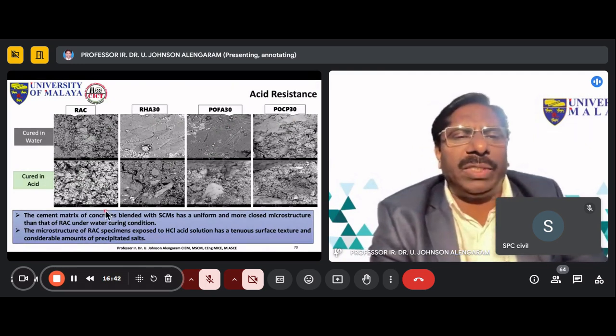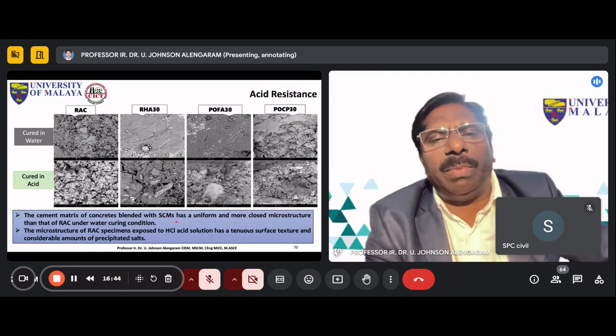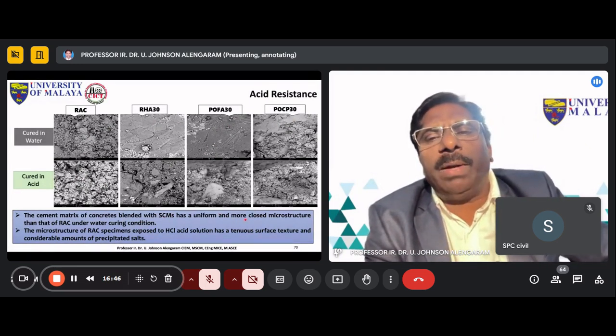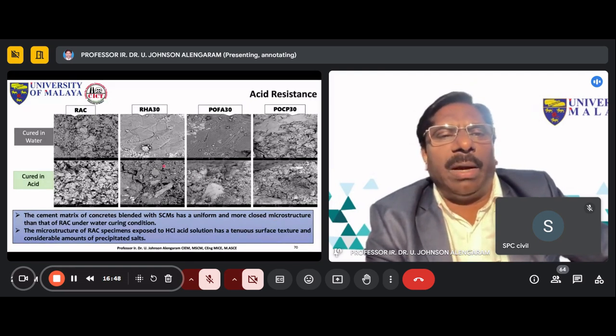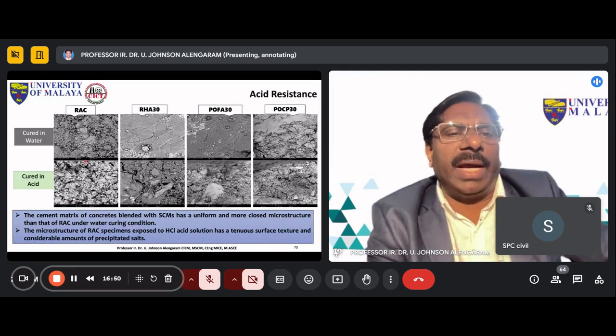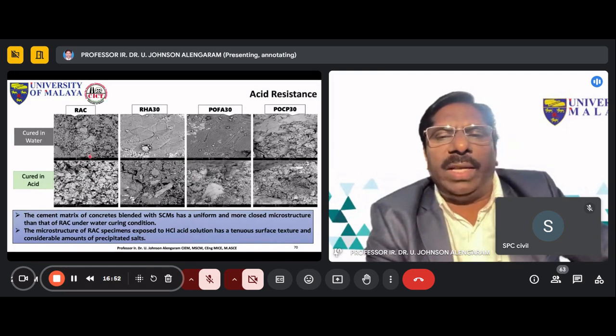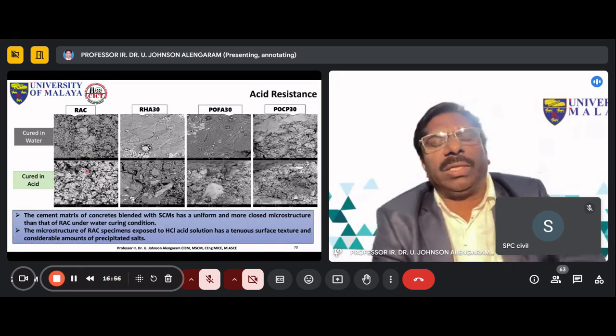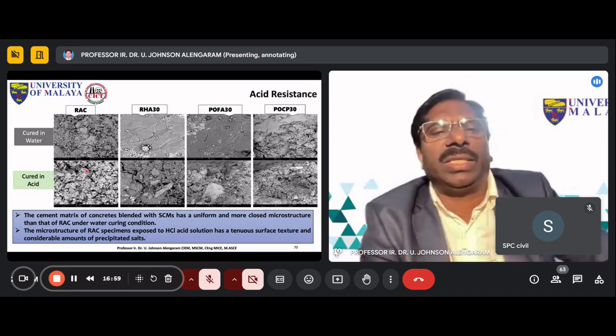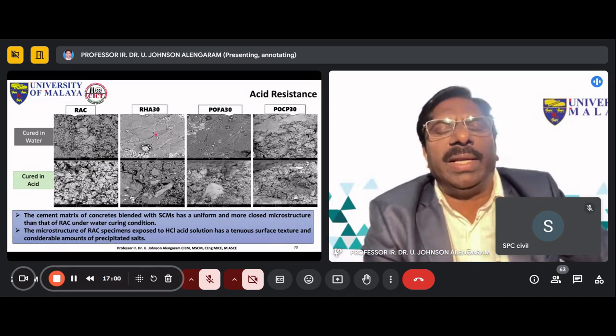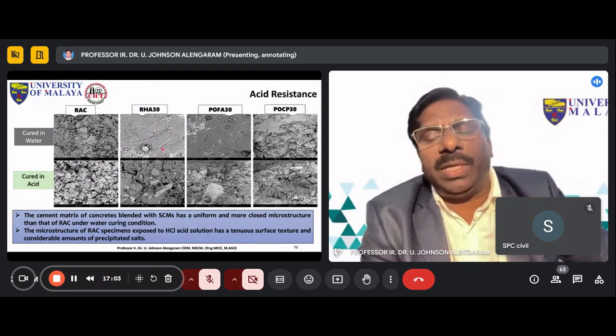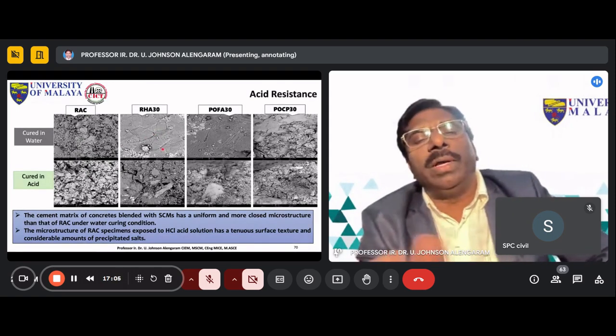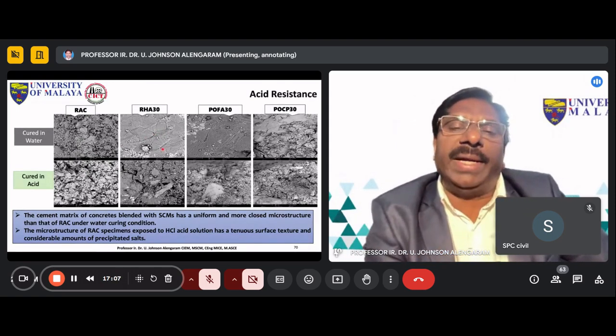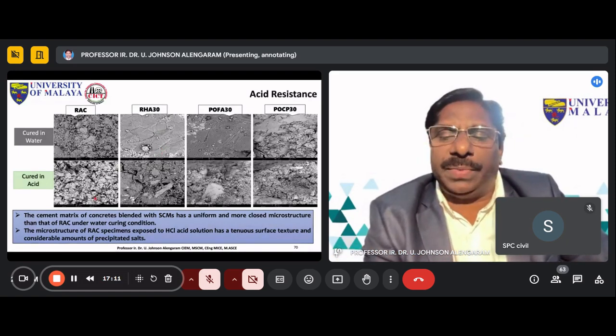So the cement matrix of the concrete blended with supplementary cementitious material has a uniform and more close microstructure here compared to the recycled aggregate concrete. Because when this texture is exposed to the acid, it has more porosity inside. But these materials, when ground, react with the calcium hydroxide and produce more calcium silicate hydrate gels, thereby the structure of the concrete is compact compared to this.